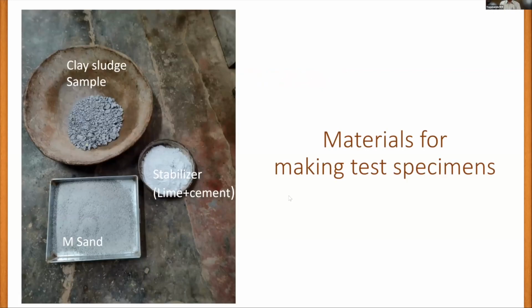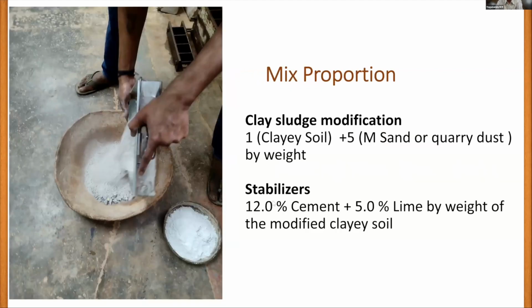And then we try to look at having test specimens. What do we do if we want to use it in construction? So clay sludge sample, then you have stabilizers, lime and cement, and then manufactured sand is what we have used here. The mix proportion, after a number of experiments, we arrived at the right kind of mix proportion to achieve the minimum wet strength of 3.5 MPa. That's the standard in the Indian standard code.